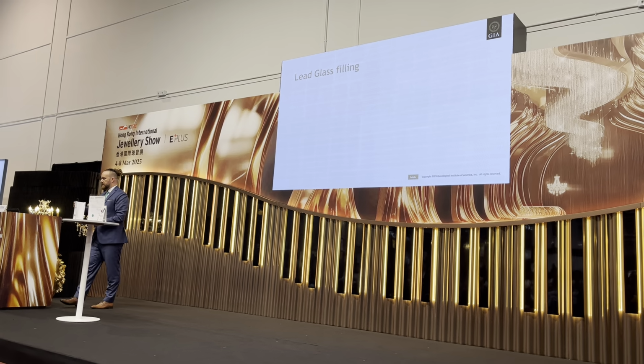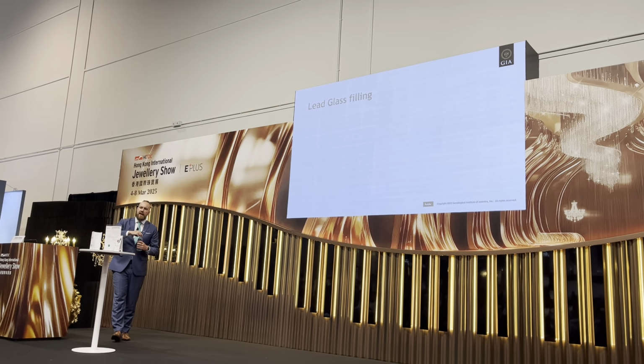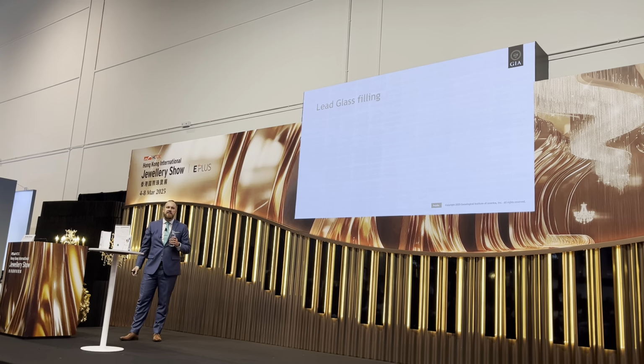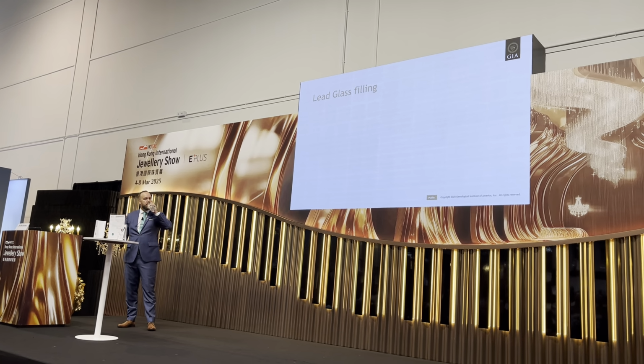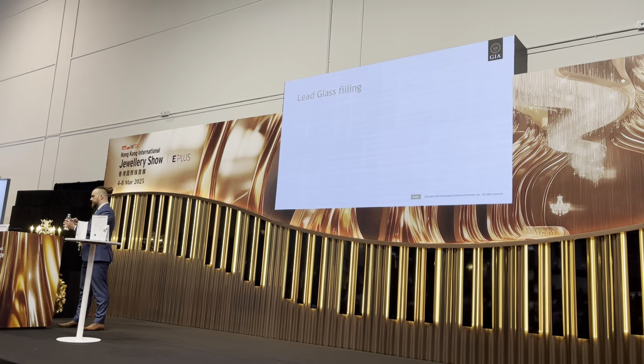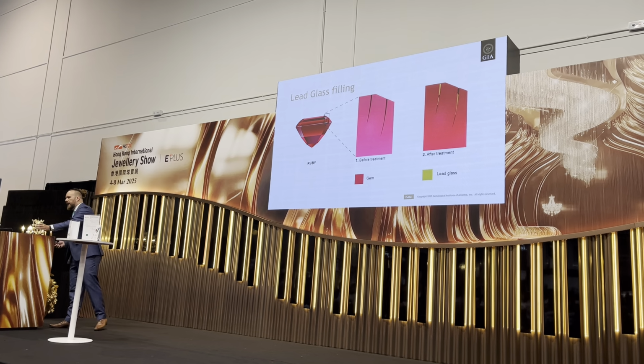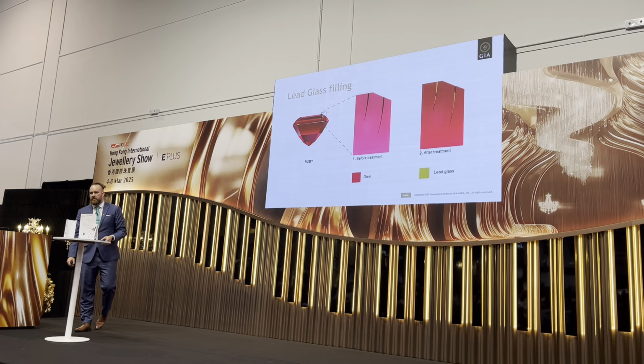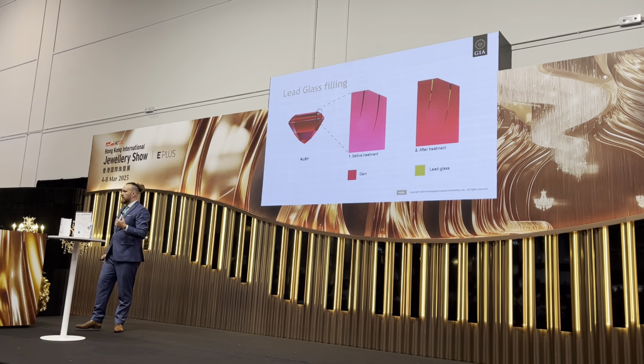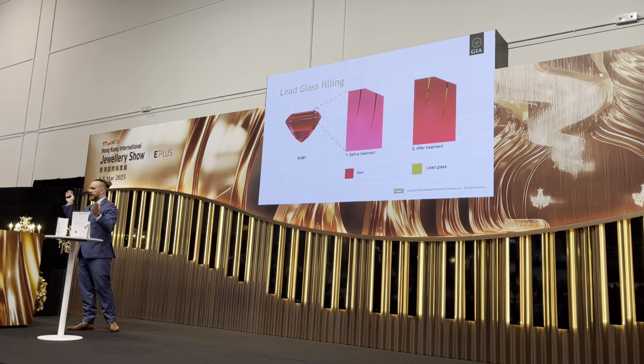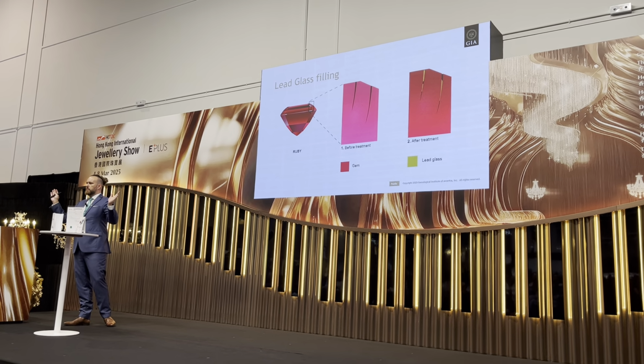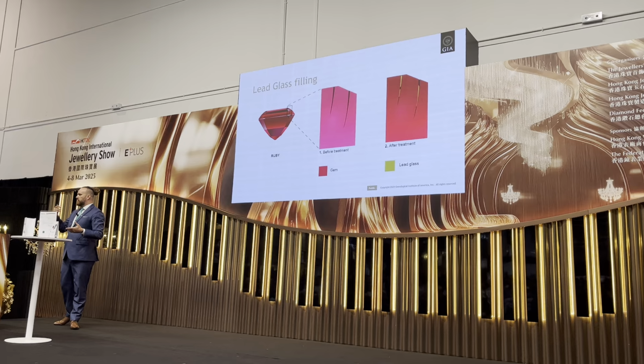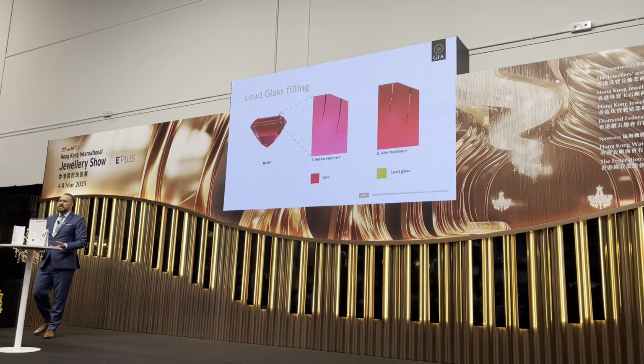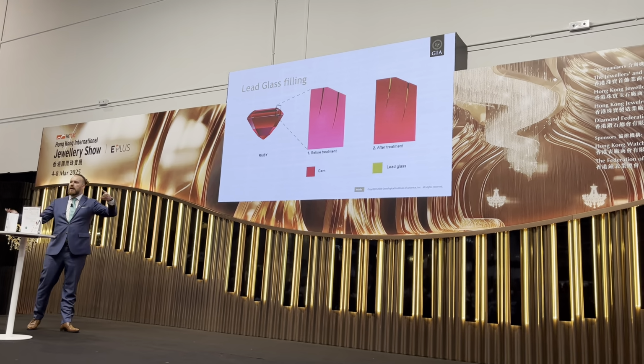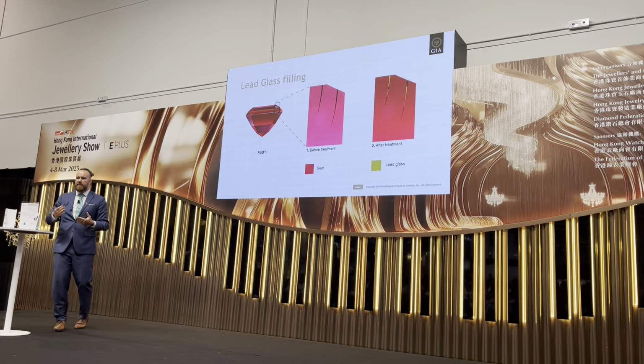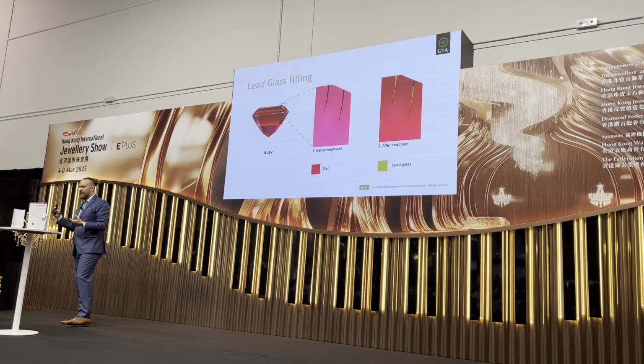Now then we have another process, a process that a lot of people frown upon, but I think it's very important to recognize, and that is lead glass filling. Now lead glass filling is very interesting, because it is not a complex scientific treatment. The easiest way I can explain it is, you have a ruby with a hole on it, you just stick the hole full of lead glass. Problem solved. That is what's happening during lead glass filling. So basically at this higher temperature, that glass will melt, it will go into the fracture, it would solidify there, and then it will completely hide the fracture.